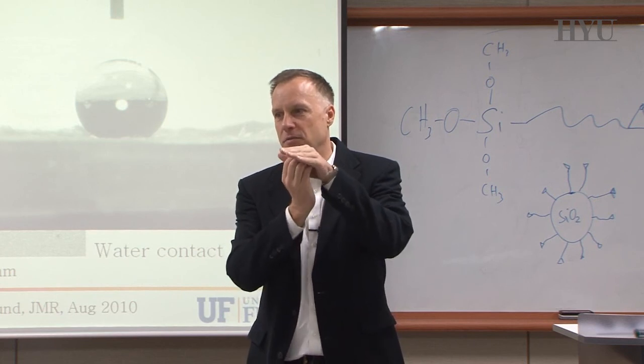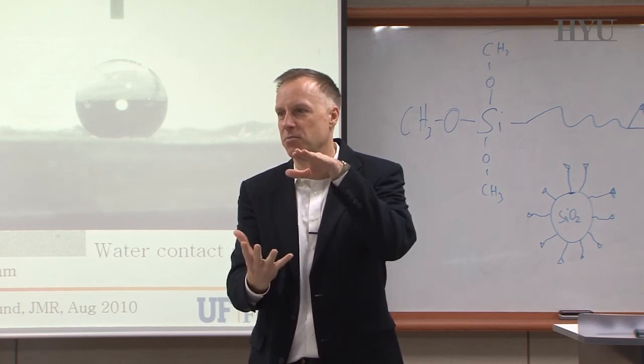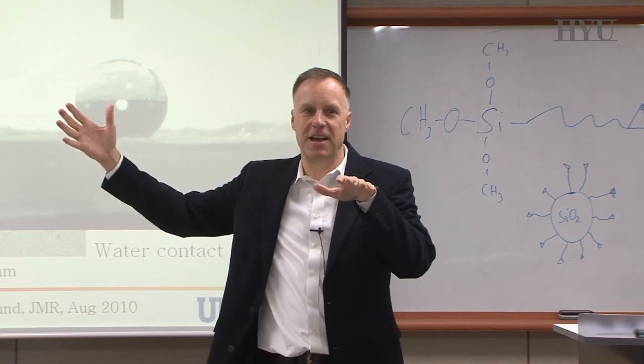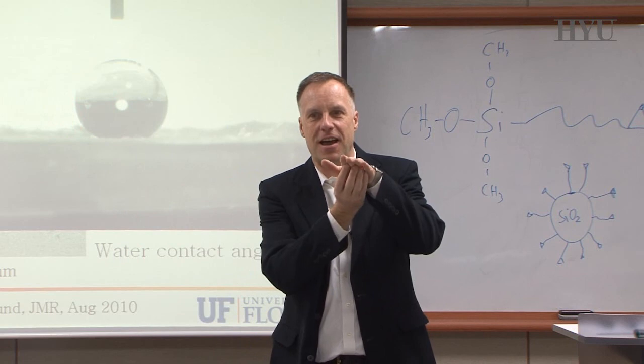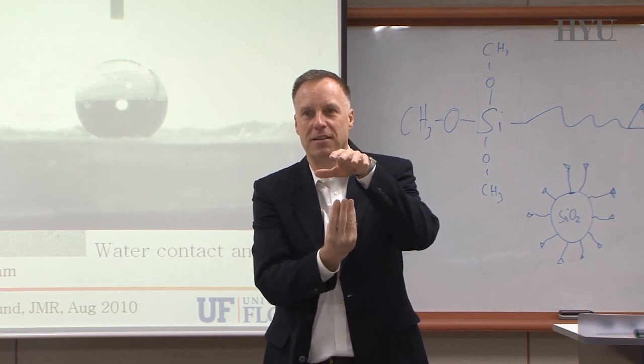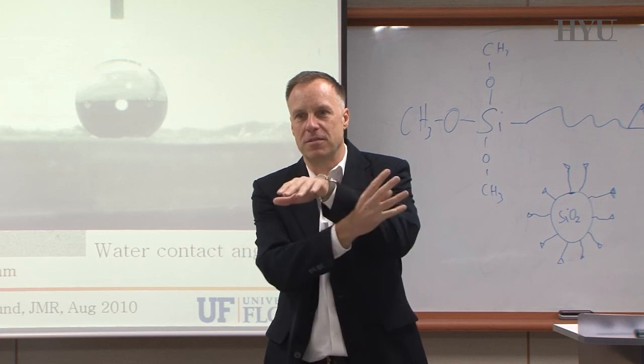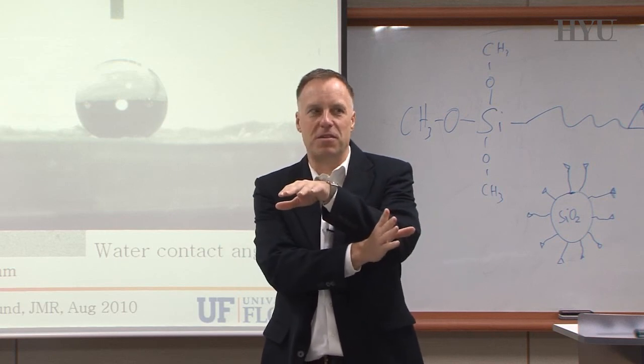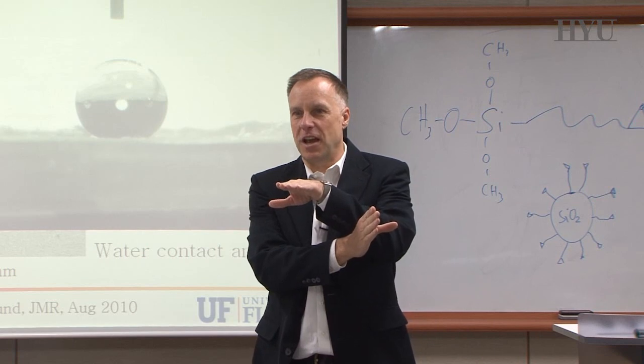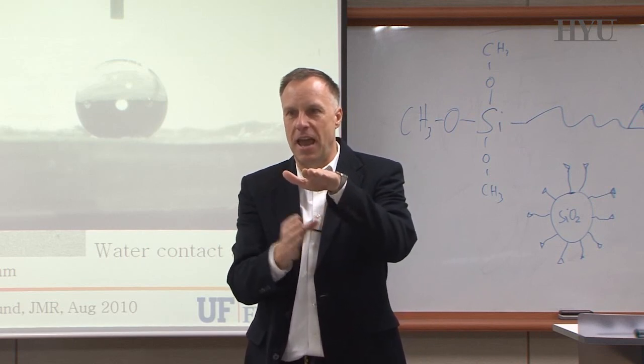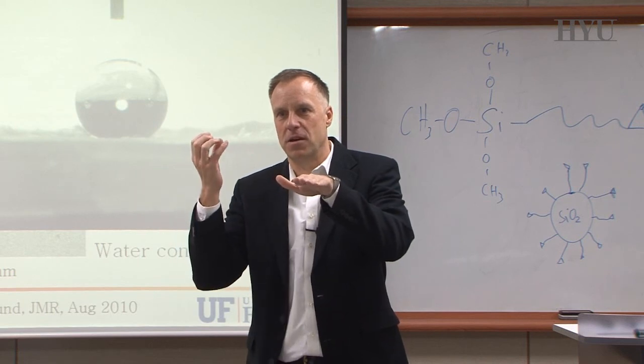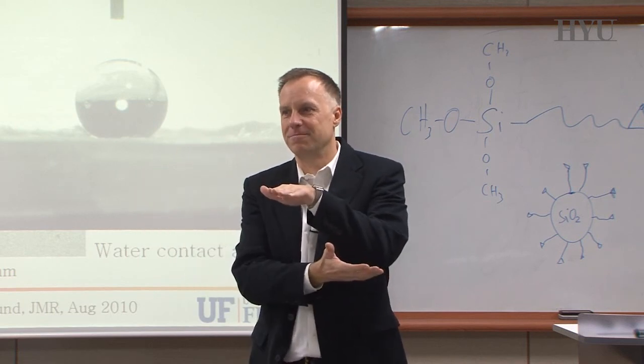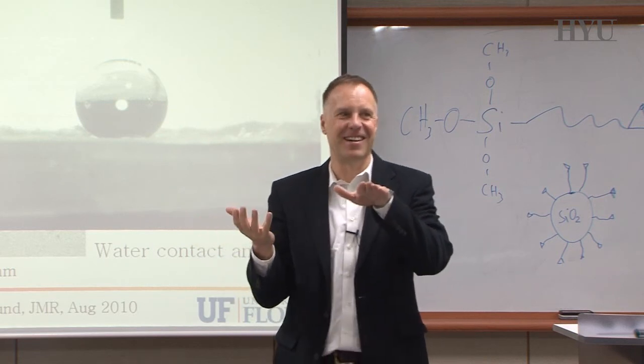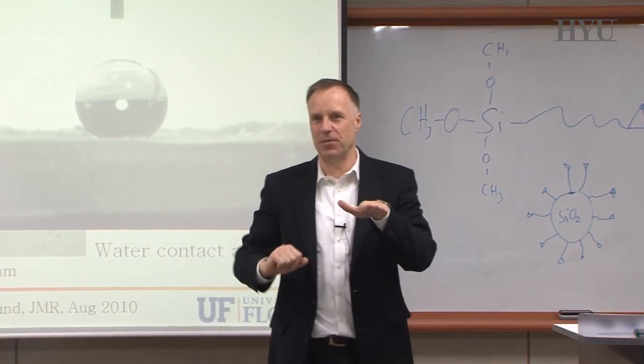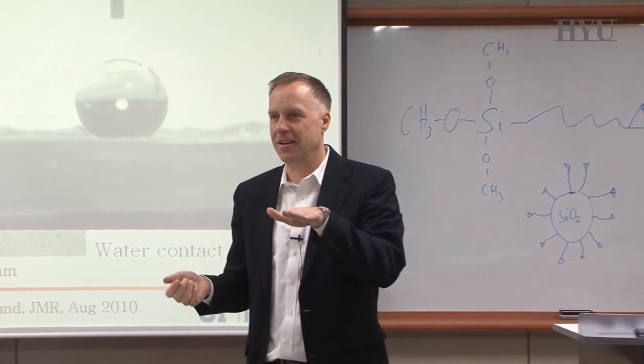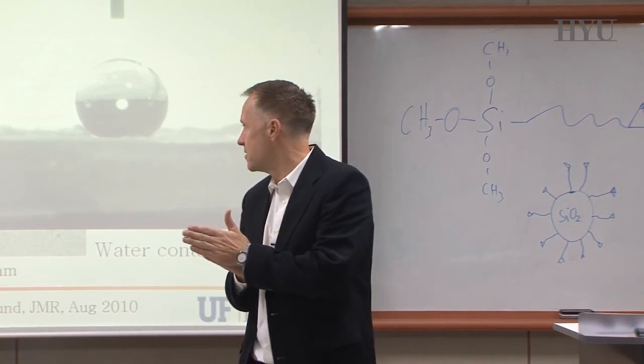Now it's a liquid in an electric field, and you start to form a cone again, and you start to electrospray. So on one side, you get the large particles in and deposit them, and then the system starts to electrospray small particles, and they can escape the system again because they're more towards the end of the system where you electrospray. So with an electrostatic precipitator, you actually change the air in the factory from micron-sized droplets to nano-sized droplets of oil. You're not removing the oil. These things are surprising, but with enough critical thinking and understanding, you can analyze these systems.